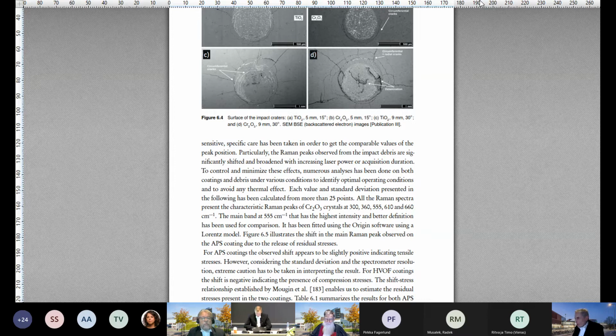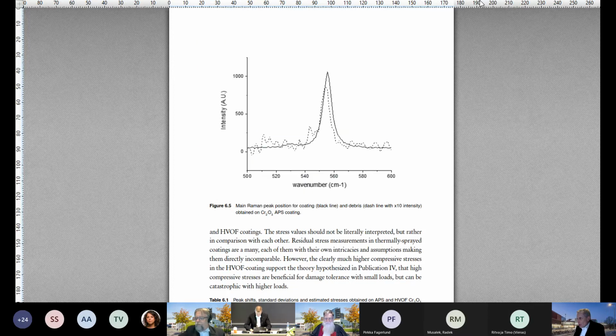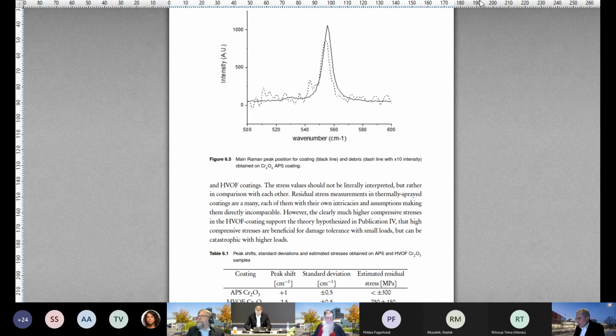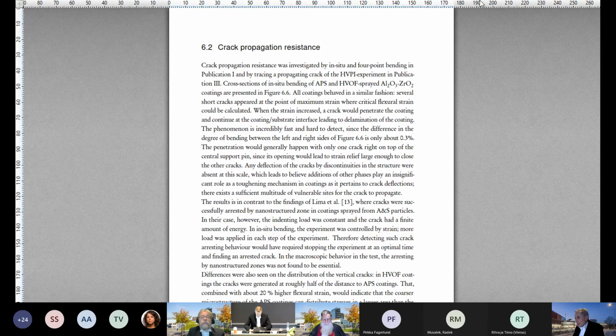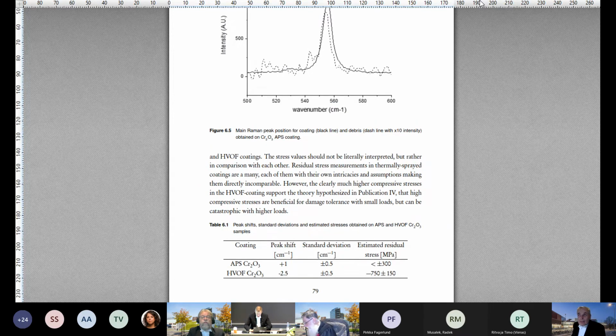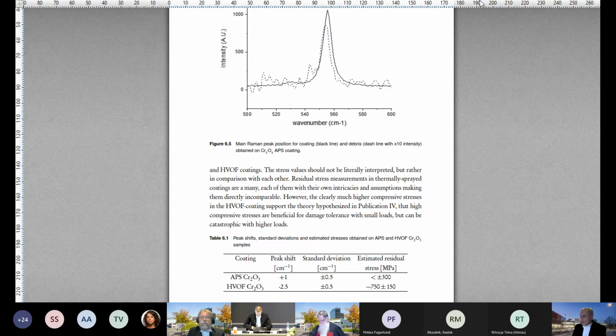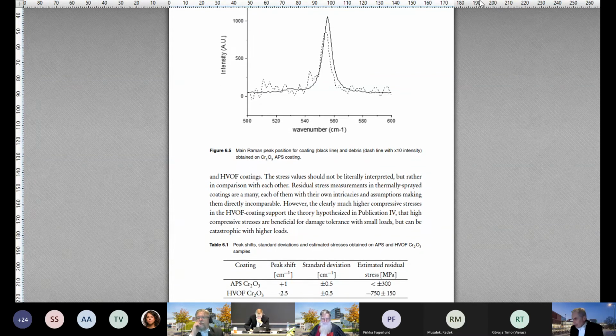Okay, one thing a little bit. I'm not 100% sure. I haven't looked at it previously, but to me it sounds like one should expect that when there is a compression, you should go to higher wave number, and when you have tension, you go to lower wave number. So in this table 6.1, it looks like the opposite. Yes. So you might want to check that once more. And if you look at the reference 183, that's what actually to me occurs. So when you have a compressed state, you actually have higher shift in the vibration phases. So the excitation should be higher.